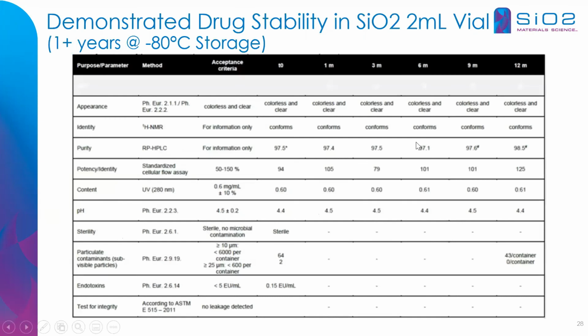So this chart here is kind of complex. It's got a lot going on, but generally, if you just look at the time along the top from t = 0 up to 12 months, and you look at the attributes, the appearance, identity, and so forth, what you'll see is that there is no change in the drug product based on these attributes over time. And that is showing a measure of stability of the drug product in the SiO2 container. So this is one of the cases where the SiO2 container performed very well at minus 80 degrees C and is really a suitable container for this application.